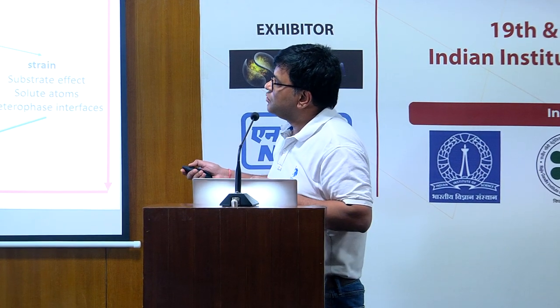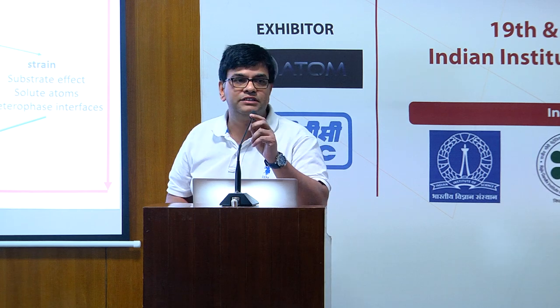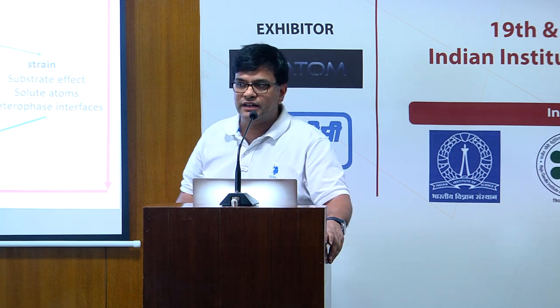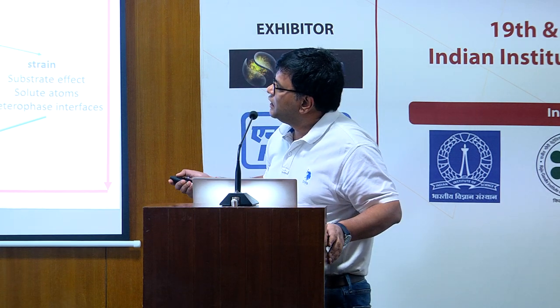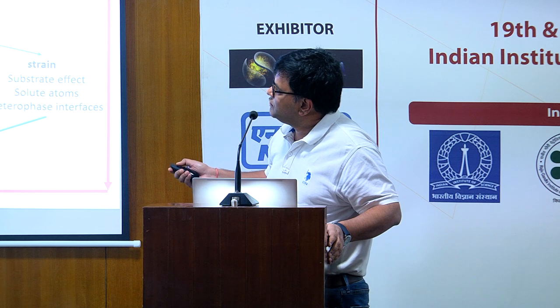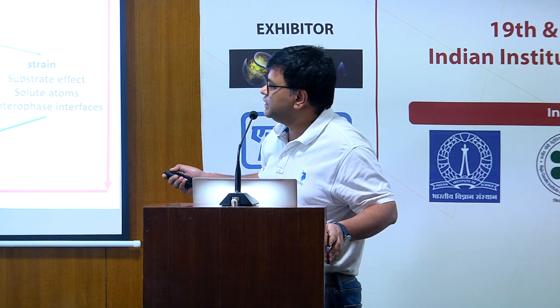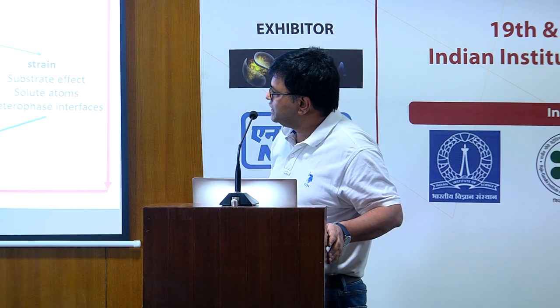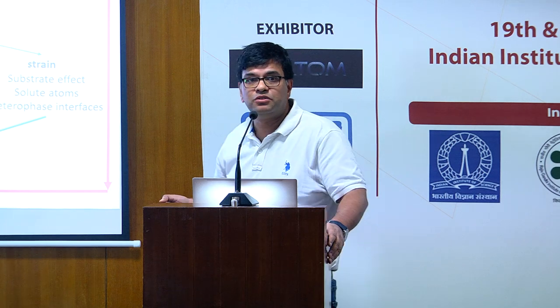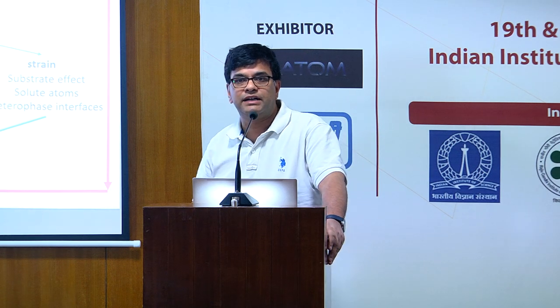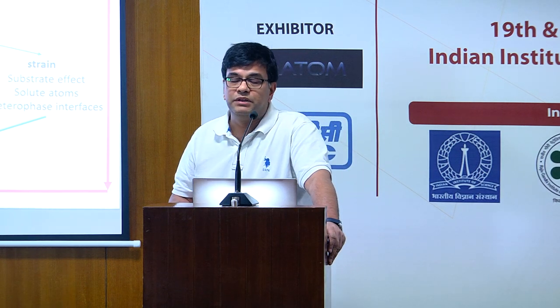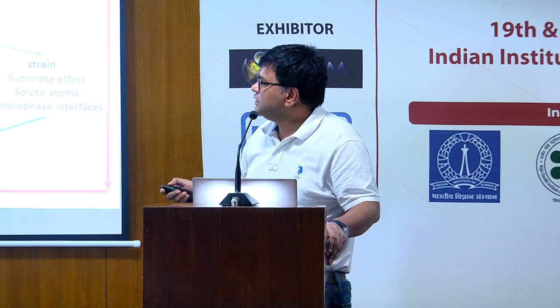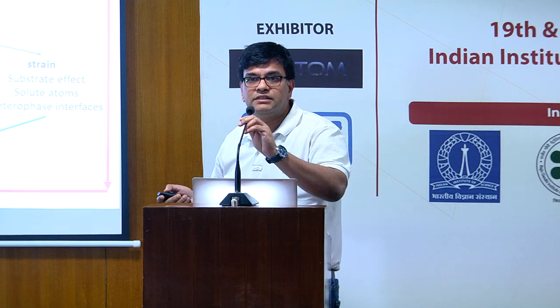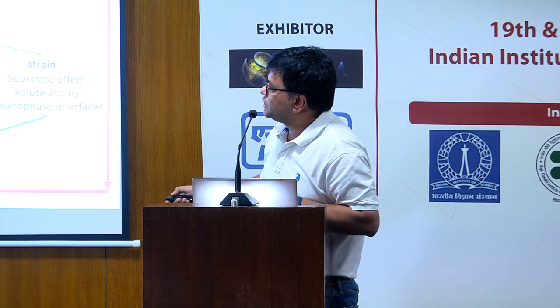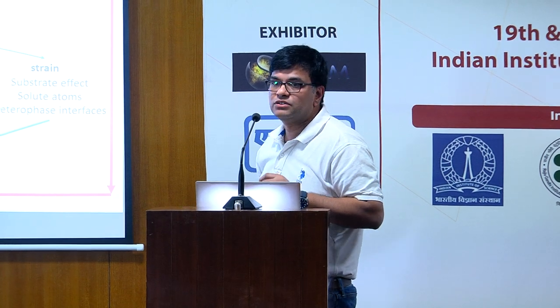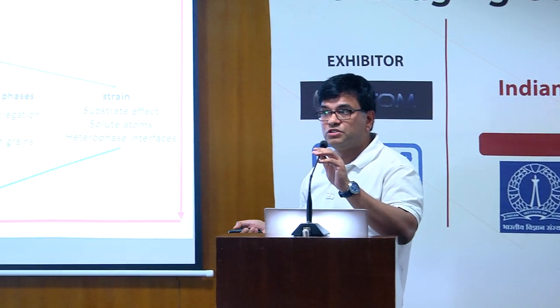The morphology of the coating is basically connected to the surface defects and cracks, and that is very highly studied. If surface defects or cracks are there in the coating, then you have enormously high corrosion. But suppose you are able to make a coating which is compact and crack free, not in a theoretical sense but in a practical sense, then one must look at the microstructure of the coating to understand its corrosion behavior or corrosion rate.